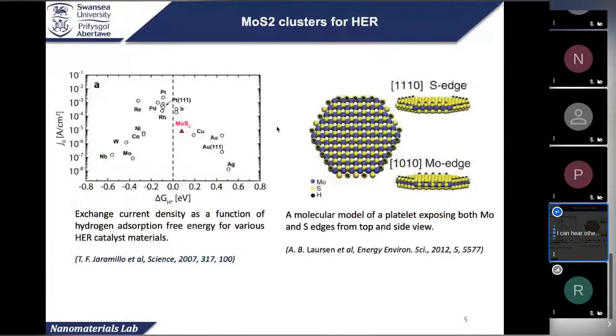So let's go to the first one. Let's come to the MoS2. On the left, there's a volcano plot showing the hydrogen evolution reaction activity of different materials. Basically, you want a material with an adsorption free energy as close to zero as possible, so the hydrogen can be adsorbed and desorbed freely, which is good for the reaction. But at the same time, you want a higher exchange current density. So that's where this plot comes from.